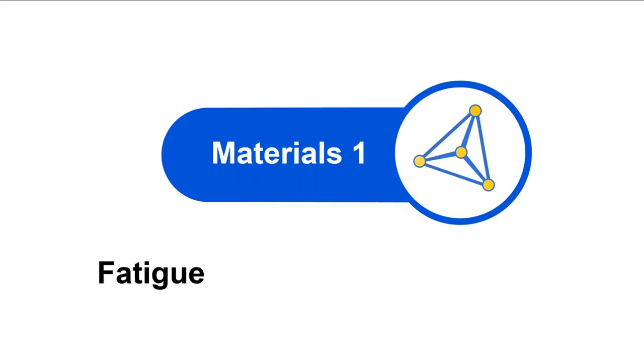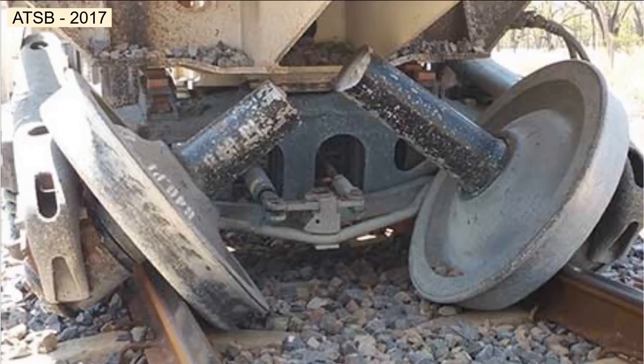Hi everyone. Welcome to a lecture that describes a materials degradation mechanism that limits the longevity of a number of applications. It was first observed at the dawn of the railways, but even today it can still present dramatic failures. Here is a failed railway axle, which was documented in 2017 in Australia. The reason why this axle failed was because of an unobserved fatigue crack, which propagated and then led to the relatively dramatic failure depicted here.